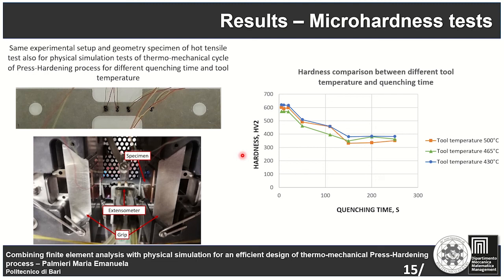On the right, you can see the graph of hardness values as a function of quenching time for all tool temperatures investigated. We can observe that if quenching time and tool temperature increase, the hardness value reduces. You know that hardness is an indicative parameter of the microstructure. Therefore, it can be assumed that as the hardness value decreases, the percentage of transformed martensite decreases and the bainite percentage increases. This means that when the hardness value remains constant, it can be supposed that there has been a complete bainitic transformation.